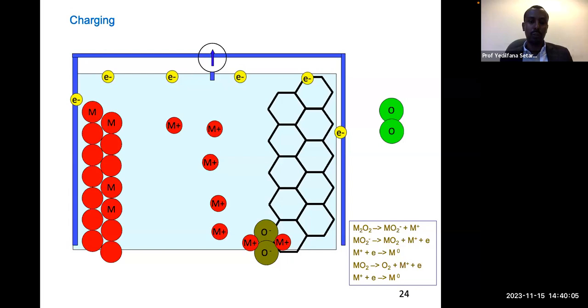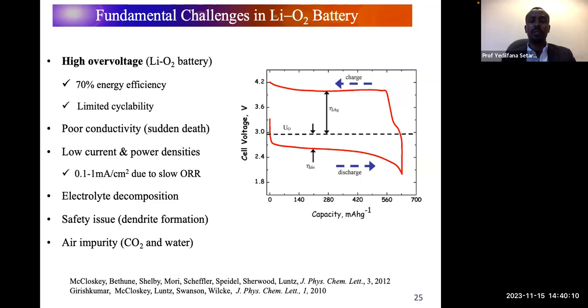So what are the challenges in lithium oxygen batteries? As I said before, they are promising, but there are a lot of challenges to be addressed before going to the market. The main challenge with the metal oxygen batteries is their high overvoltage. As you can see here, the nominal or theoretical voltage that we are expecting to get from this battery type is around 3 volts. But as you can see on the bottom curve, experimentally we found around 2.6 volts with a capacity of 560. So the difference between 2.6 and 3 is what we call discharge overvoltage. And the one with charging is actually extremely large.